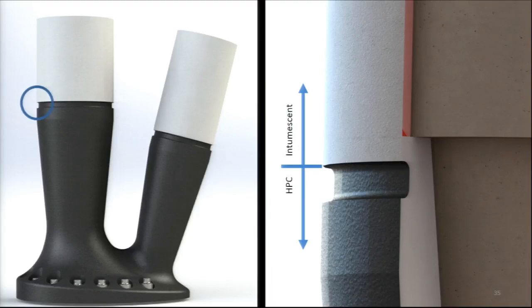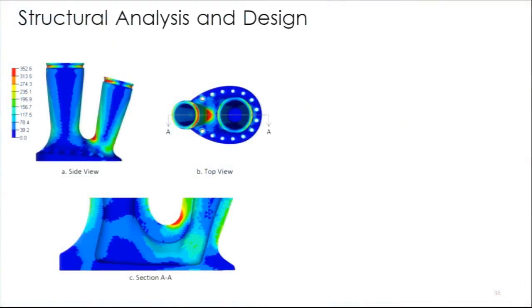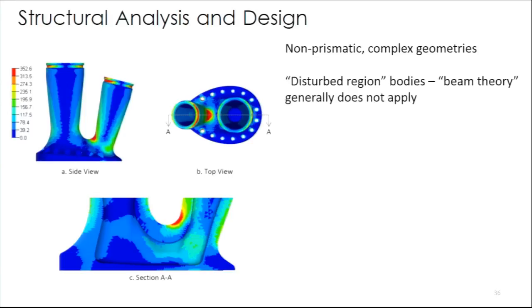You can see the wall of the hollow section, the partial joint penetration weld, all being covered with intumescent coating, and then a purposeful reveal being cut into the casting to emphasize the difference between the pipe and the cast node. From a structural analysis and design perspective, ourselves as casting designers, we conduct complex finite element analysis, and that's because castings are non-prismatic complex geometries. They're disturbed region bodies. Beam theory does not apply. You can't just use beam theory to determine the forces in these elements. They're disturbed regions or D-region elements, and so you typically need finite element analysis to determine the stresses in the casting.